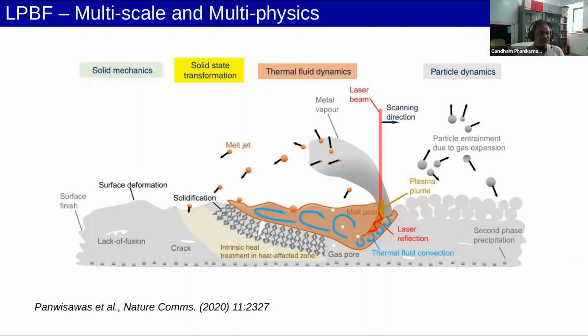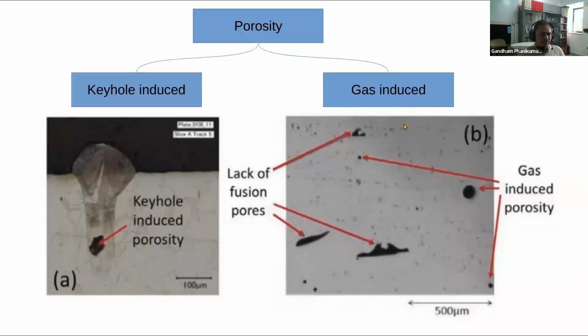So this is something that in the physics of the additive manufacturing, laser powder bed fusion, for example, you are already familiar how the laser molten pool is moving, and when the scanning direction is to the right, and then as it is moving, then you see that this is a region where the solidification is happening, and you see that the various phenomena are taking place, various defects are possible, etc. Okay, now there are two. If you see porosity in an additive manufactured component, it might have had basically 2 origins. The first origin is because of keyhole.